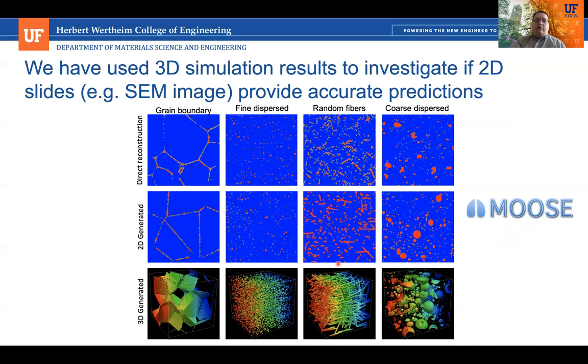But we wanted microstructures that were similar to these from the actual experimental data. So we reproduced the microstructures from the experiments. And then we came up with ways of generating microstructures that had very similar characteristics. And we compared their characteristics and also the thermal conductivities and made sure that they compared well. And once we had this approach working in 2D, then we just ran it in 3D and we have our 3D microstructures.